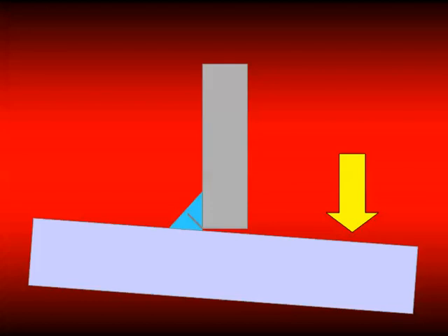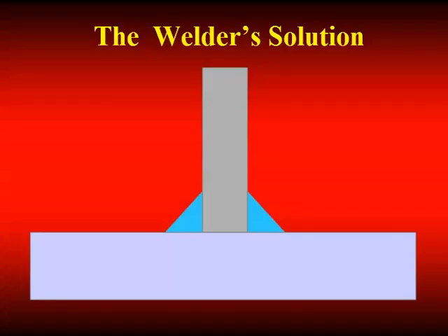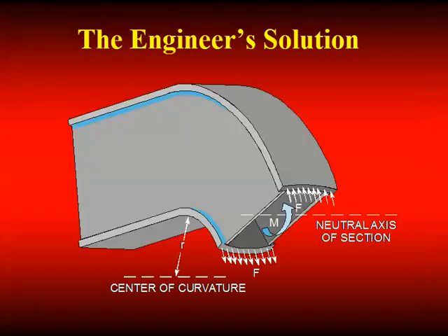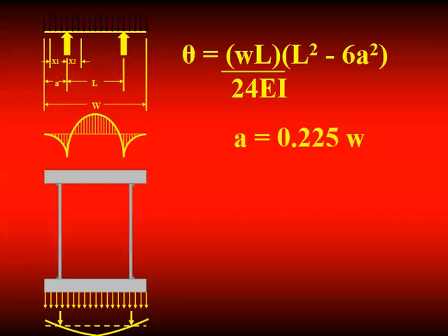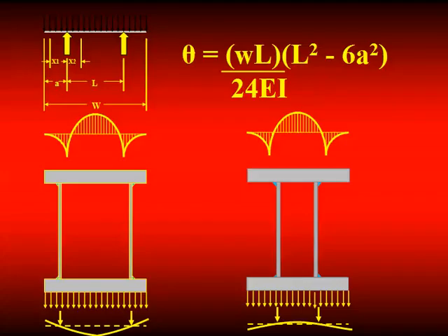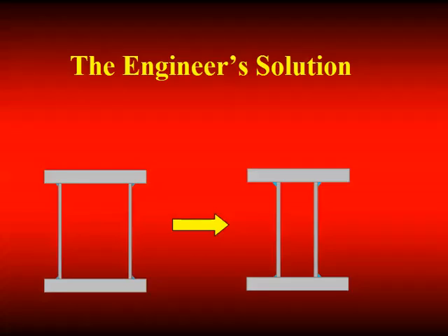So the welder had an idea and said, well, we need to put a weld on the inside. And that's a good idea, but it's kind of hard to get in there. And then the engineer had a different idea, and he said, well, there's an inflection point on a beam subject to bending. If I move these supports in to the point of inflection, I have no relative bending at that point in time. And indeed, that's what was done, and eliminates the bending stress on the weld, and the problem went away. So the principle is don't put welds into bending. Lots of solutions to keep it out of bending.